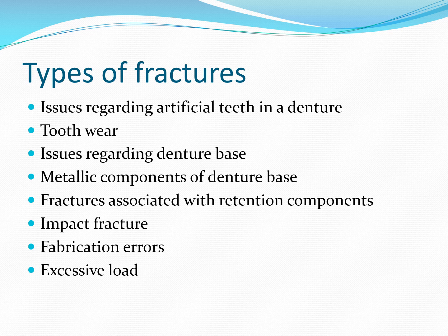But when we give relief, the denture here becomes thin, and if the frenum is high and the frenal notch is big, the upper maxillary denture will fracture easily. Other causes are retentive component issues, impact fracture, fabrication errors, excessive load, and heavy mastication.